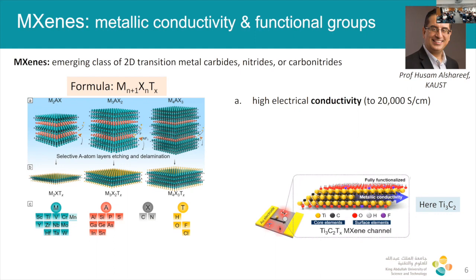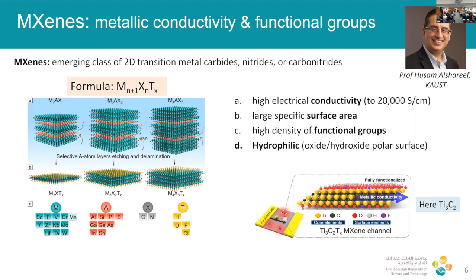Firstly, the high electrical conductivity. This is actually an order of magnitude higher than reduced graphene oxide. So very conductive, of course, very large specific surface area, but you also have these functional groups. Typically in any other 2D nanomaterial, 1 and 3, so A and C, are always in a trade-off. But in this material, it's not in a trade-off, which makes it just perfect for us for use in electrochemical biosensors, right?